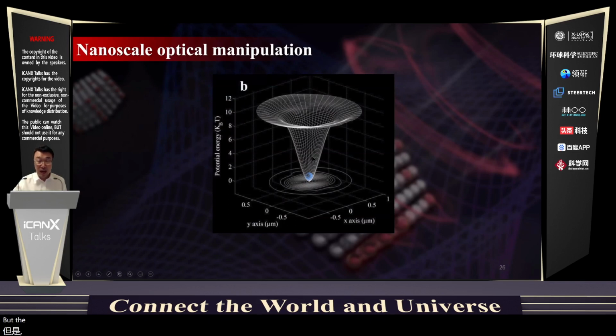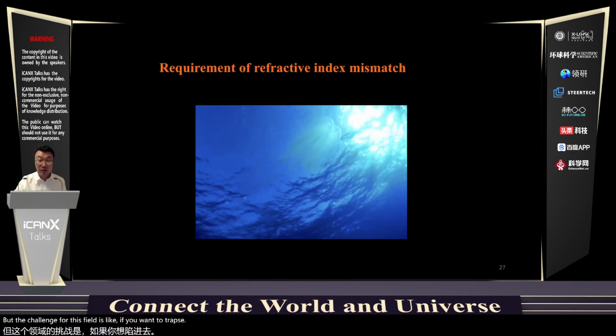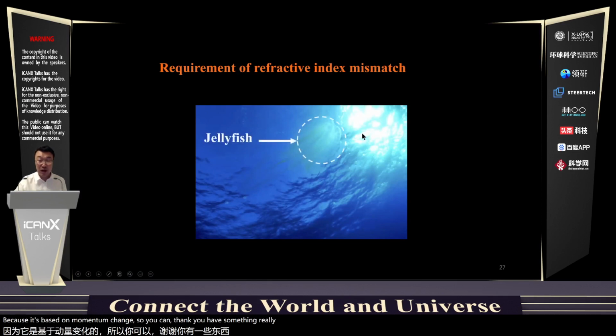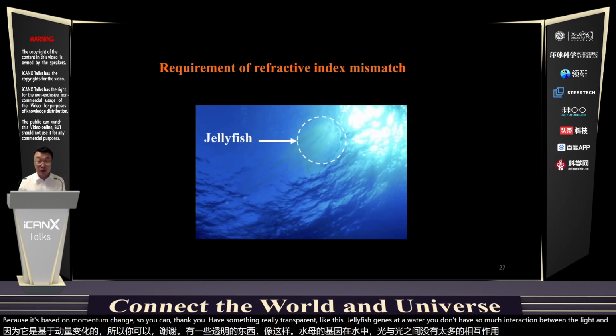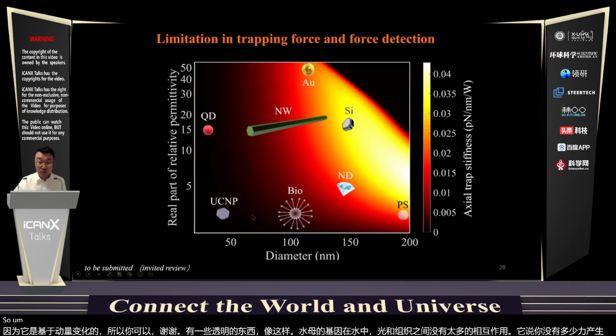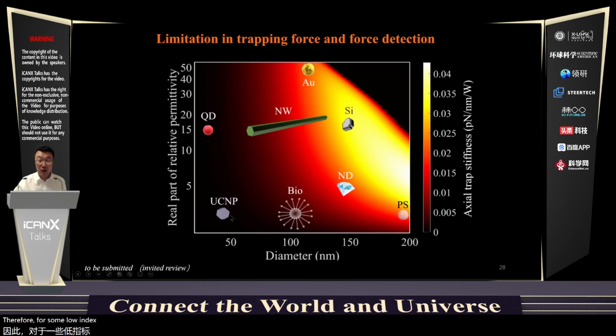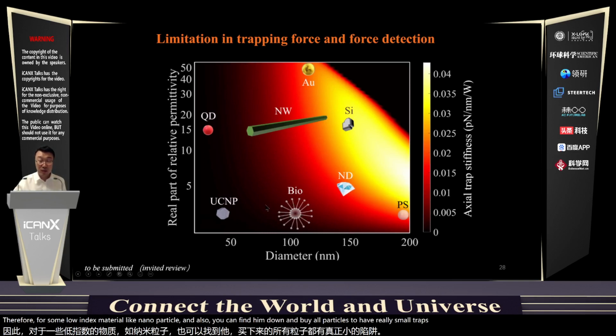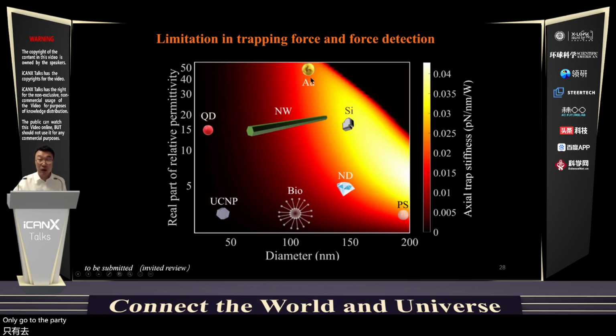But the challenge in this field is that if you want to trap something, you have to have a refractive index mismatch because it's based on momentum change. If you have something really transparent, like this jellyfish inside the water, you don't have much interaction between the light and the tissue, and then you don't have much force generation. So for low index materials like nanoparticles, quantum dots and some bioparticles, they have really small trap stiffness and trapping force, and they also have less scattering, so they are hard to detect. Only the gold particle is the popular one.